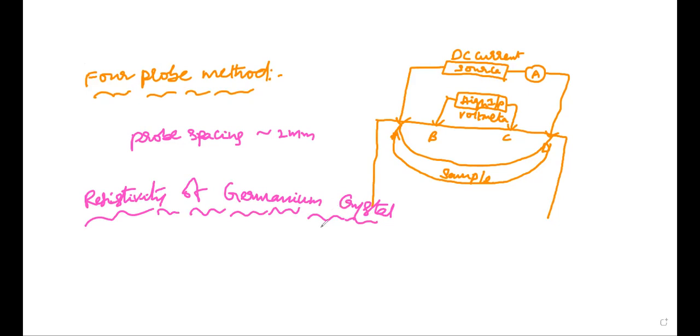In order to use this four probe method on a germanium crystal, it is necessary to assume that the resistivity of the material is uniform in the area of measurement, and a non-conducting boundary is produced when the surface of the crystal is in contact with an insulator. We will write the derivation of the equation. So first, resistivity measurement.